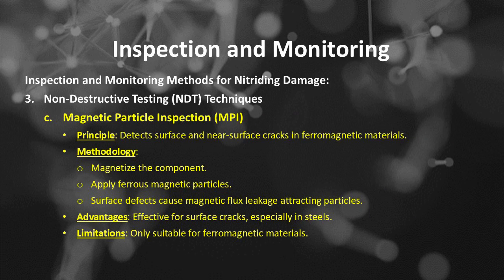The NDT technique is magnetic particle inspection, or MPI. The principle of MPI is to detect surface and near-surface cracks in ferromagnetic materials. The methodology of MPI includes magnetizing the component and applying ferrous magnetic particles; surface defects cause magnetic flux leakage, attracting particles. The advantage of MPI is that it is effective for surface cracks, especially in steels. The limitation of MPI is that it is only suitable for ferromagnetic materials.